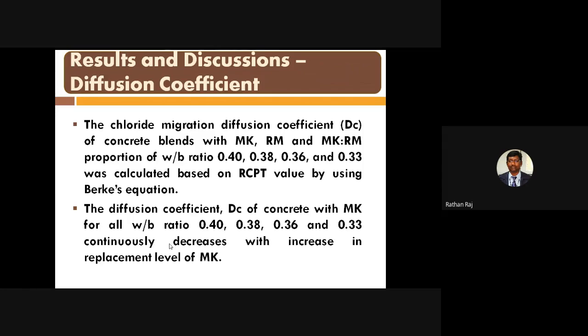80:20. And also there are 4 different types of high strength concrete developed with varying water binder ratio. The water binder ratios are 0.40, 0.38, 0.36, and 0.33, which shows M30 grade, M40 grade, M50 grade, and M60 grade. Starting from 30 Newton per mm squared to 60 Newton per mm squared was designed based on the mix proportion. So this diffusion coefficient was calculated based on the RCPT value only, rapid chloride penetration test value.